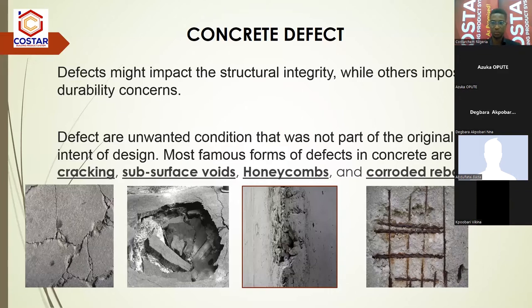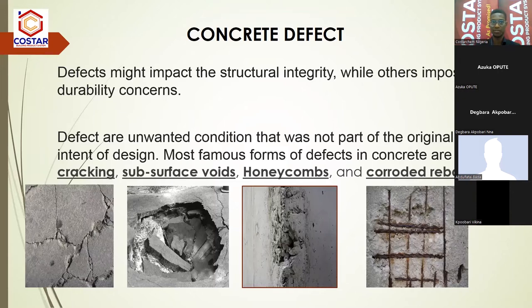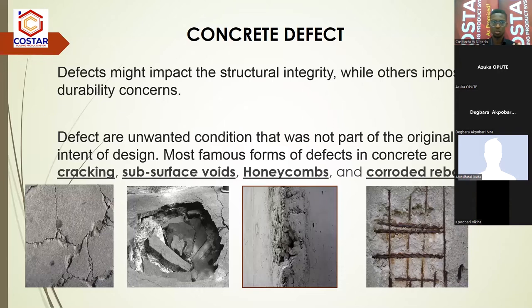And finally, corroded rebars is another defect. This occurs whenever your concrete has contact with moisture and air. You can't avoid the rebar from making contact with moisture, because when the concrete is cast over the rebar, the concrete touches the iron and contains water in it. But once it solidifies, it ought to be well compacted enough to disallow continued contact of water and air, because those are the two major components that cause corrosion.